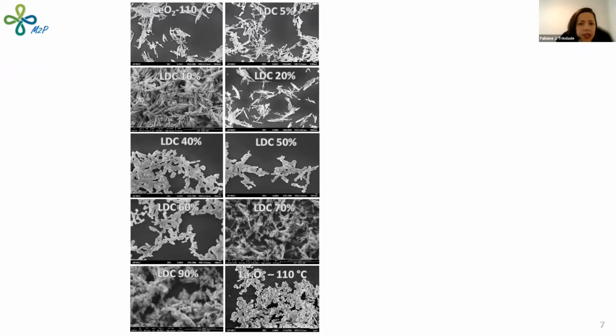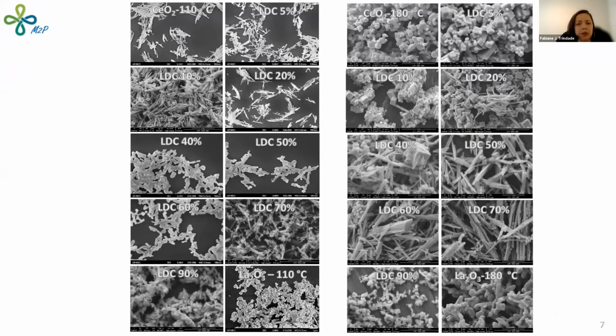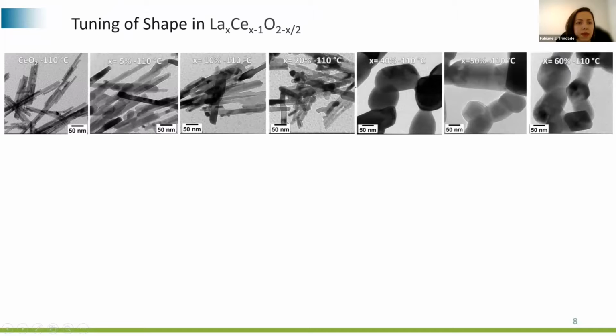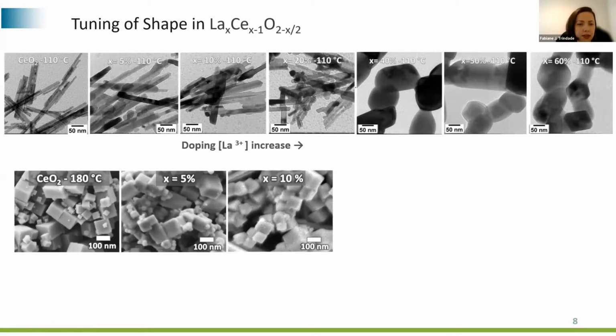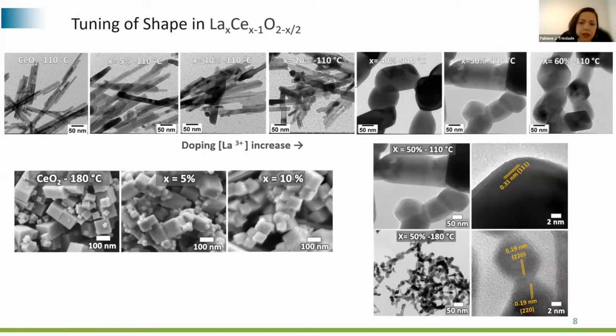As I said, we controlled these nanomaterials by changing the synthesis temperature: 110 degrees for nanorods and 180 degrees for the nanocubes. But above 20% lanthanum, the Ceria synthesized at 180 degrees turned into nanowires as well, which we can see in more detail with the TEM images. As you can see here, the 110 degree nanorods turn into oriented attachment rods with increasing lanthanum concentration. And the nanocubes synthesized at 180 degrees, up to 10%, turn into nanorods as well, oriented attachment, but the particles are smaller than at 110 degrees.